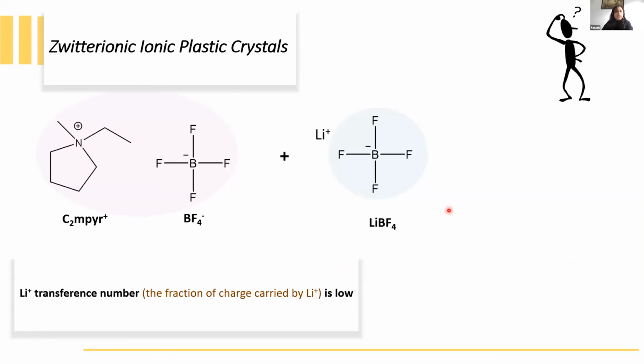So the question is, can we still improve the properties of plastic crystals in terms of having an even higher target ion transference number? In the organic ionic plastic crystal, as I mentioned, when we add a target ion into these materials, for example lithium ion for lithium devices, we normally want only lithium ion to move through the electrolyte to do the electrochemical reaction. But in the case of plastic crystals, all ions, including the ions in the matrix of the plastic crystals, are also mobile. So we can improve the fraction of charge that is carried by only lithium ion. That is called the lithium transference number.